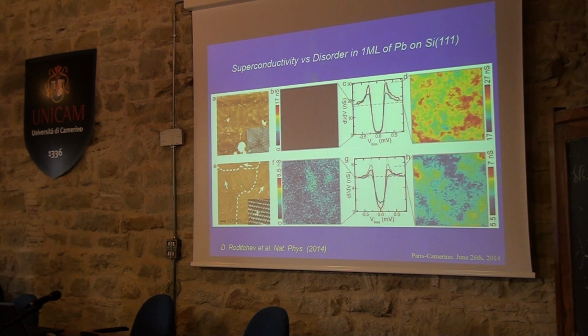Okay, so it means that this is a kind of interface superconductivity between lead and silicon. Yes, it is interface superconductivity, we believe, in which the electronic density is given by lead, of course, and probably the phonons are sort of mixed phonons of silicon and lead, but for the moment we cannot say very strongly about this.